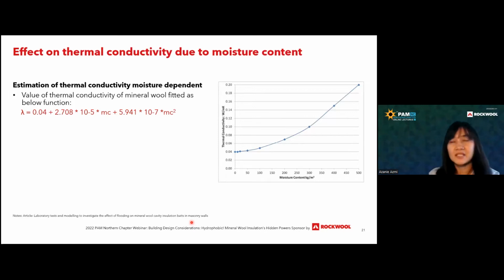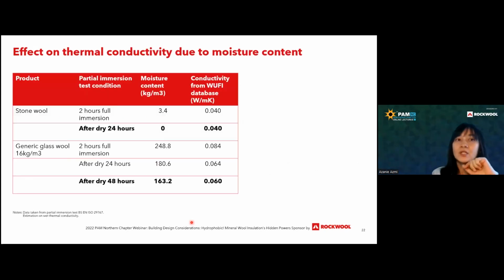So this is actually an estimation. You look into how much this moisture content is and what the increase of that thermal conductivity is. So I based it back on that test standard, the one that you look into, the partial immersion test. So I take the value of that moisture content. Let's say here, for example, Stonewool, it's around 3.4 kg per meter cube. Previously I talked about kg per meter square; this is kg per meter cube, which you need to divide by the thickness.